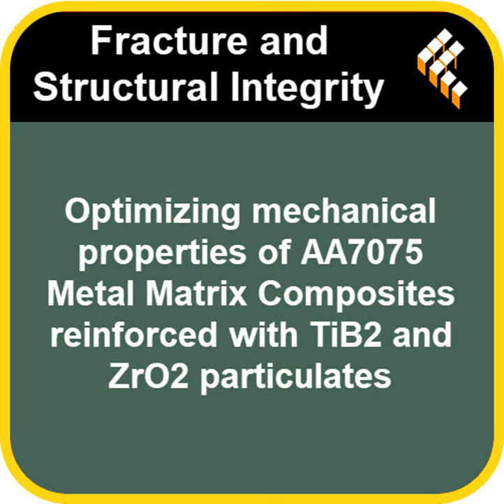Okay, so what about the other compositions, the 2% and 6% zirconia? Well, contrast that with the 6% ZrO2 sample. There, they saw a noticeable particle agglomeration, clumping, and the distribution was much more heterogeneous, uneven. Why would that happen? Too much powder? Essentially, yes. At higher loadings, the tiny ceramic particles have more surface energy, and they tend to want to stick together rather than spread out nicely in the melt.